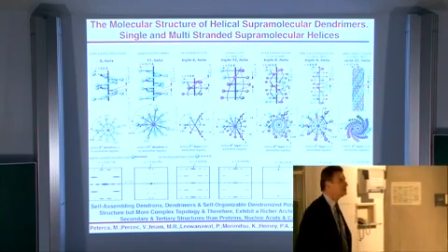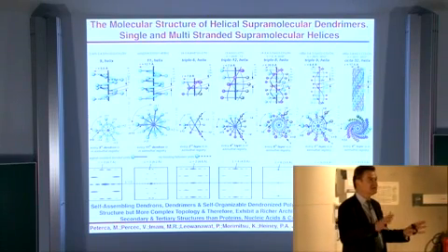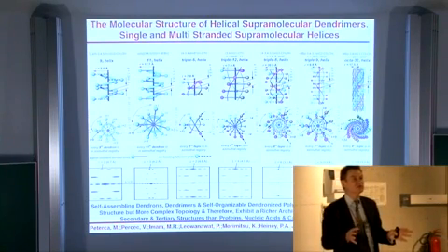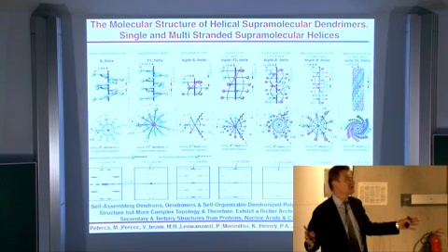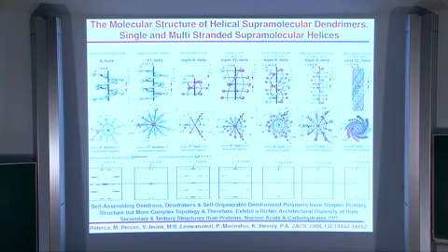And in the meantime, we have demonstrated a lot of other structures. So there is a very nice news here, and there is a very sad news. This molecule displays a larger diversity of helical structure than protein, nucleic acid, and carbohydrates altogether. That's a bad news and a nice news at the same time. Why is that they display so large? Because there is more conformational freedom. You cannot freeze a certain conformation like in the peptide bond via hydrogen bonding and higher rotational barrier. You just move permanently and you have more complex structures.